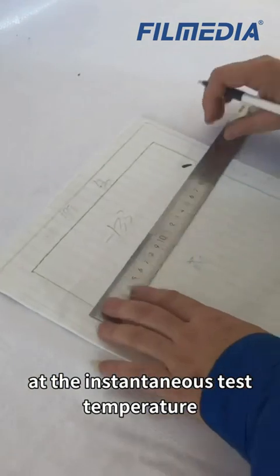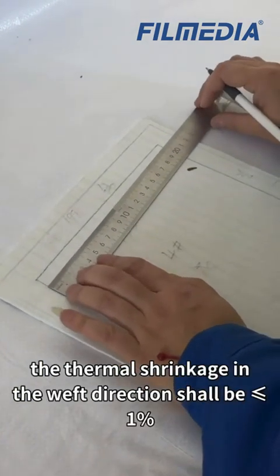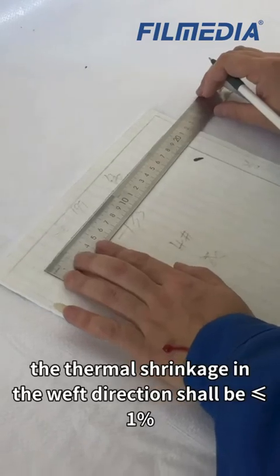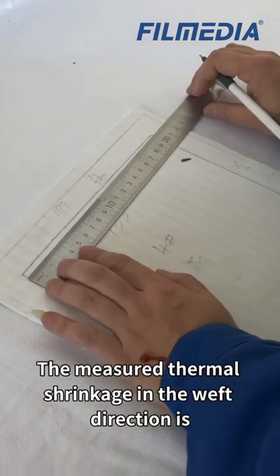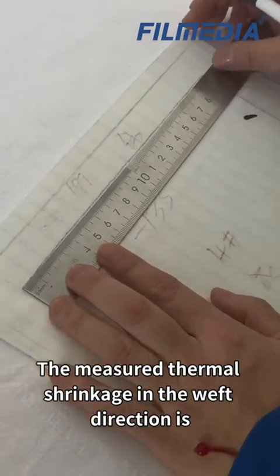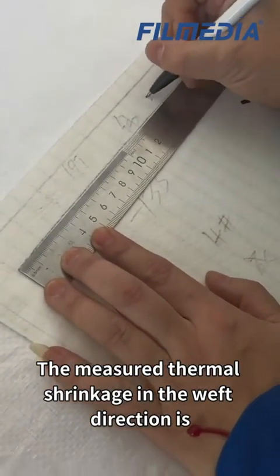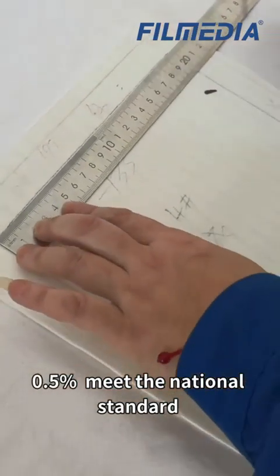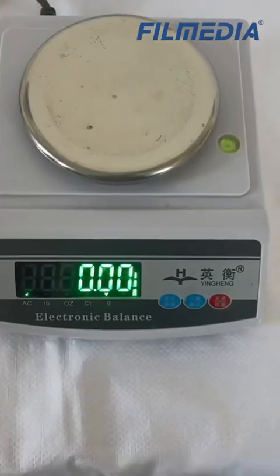According to the national standard, at the instantaneous test temperature, the thermal shrinkage in the weft direction shall be less than or equal to 1%. The measured thermal shrinkage in the weft direction is 0.5%. Meet the national standard.